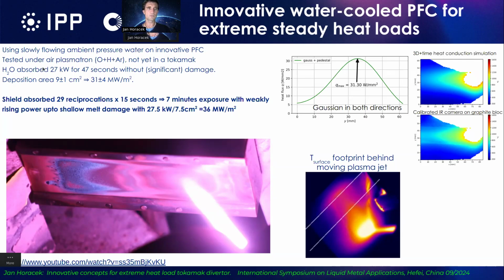What we achieved so far was that we could cool down 27 kilowatt power of our air plasmatron for nearly 1 minute without significant damage on the surface of the cooling component. And we measured that the value which was put there was 31 megawatt per square meter. This measurement was quite tricky because we had to take a piece of graphite and smash it with the same plasma and measure with infrared camera the footprint on the surface and use the heat conduction simulation and compare it with the infrared camera. And from this, we derived that there is 31 megawatt per square meter.